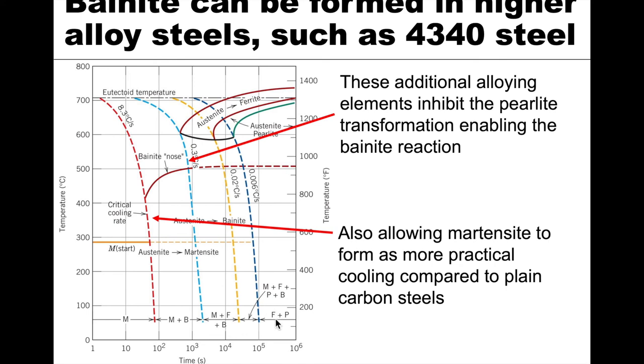With the complex 4340 diagram there are many microstructure regions. Very slow cooling produces ferrite plus pearlite. An intermediate range yields ferrite, pearlite, bainite, and martensite because the pearlite transformation is incomplete. A faster range produces ferrite, bainite, and martensite — missing the pearlite reaction. Missing the ferrite transformation as well gives bainite and martensite only. Finally, the critical cooling rate just misses bainite, producing only martensite.